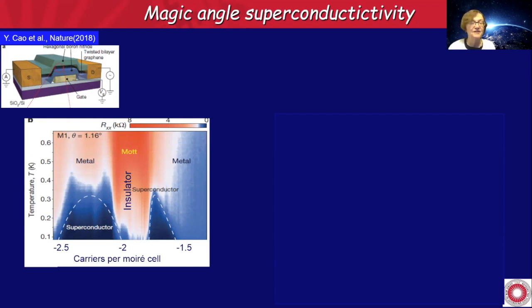So when you have 2 electrons in this 8-electron band, they saw that you have an insulator, and the insulating phase was flanked by 2 superconducting domes. Inside these domes, the sample went superconducting. And the superconductivity here was pretty pathetic. The critical temperature was below 1 degree Kelvin. So nobody would get excited about it.